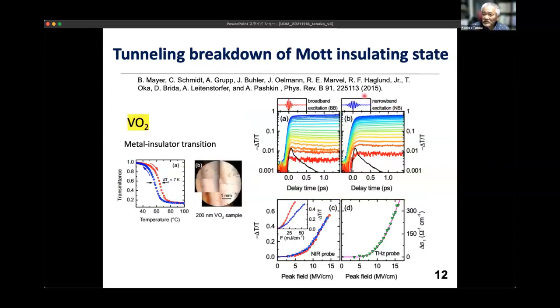Actually, in 2015, the University of Konstanz group reported tunneling breakdown of the Mott insulating state in vanadium dioxide using a mid-infrared laser or multi-terahertz light. They obtained a very beautiful breakdown to the conducting state after irradiation like this. This is a transmission spectrum, and they obtained some linear dependence on the peak field. This is what is predicted by theory for tunneling breakdown of a Mott insulator.